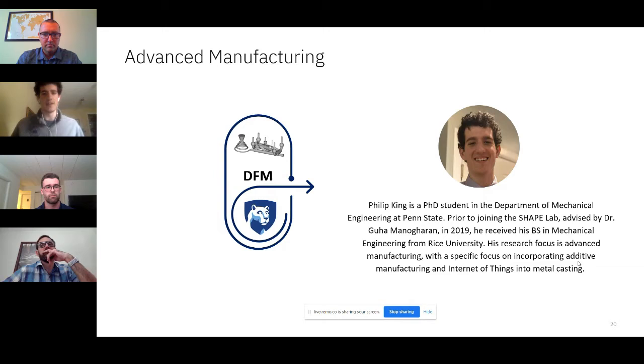Hello, I'm Philip King. I'm a PhD student, also in the Shape Lab under Dr. Manoharan. My research focus is primarily in novel rigging geometry, so these conical helix and parabolic sprues that are only able to be manufactured via 3D sand printing. And then also another aspect of my research is in embedding sensors into sand molds using 3D sand printing, so we can actually print a mold with a little cavity and place a sensor in there, and then able to get data during filling and solidification that otherwise would be unavailable to us.